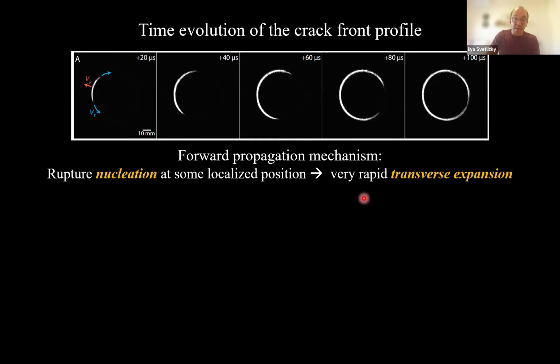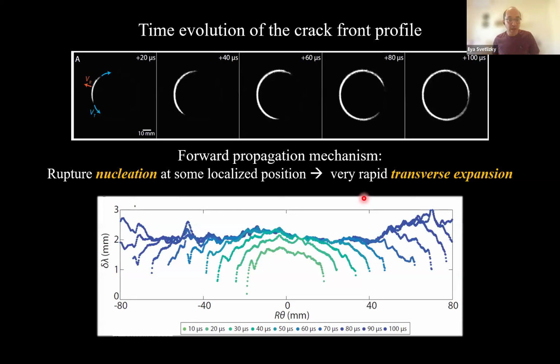So the forward mechanism is that rupture nucleates and expands through a very rapid transverse expansion. So this is how you start with the circle and you finish up with the circle. And we can track the crack front. So the colors correspond to different time steps. The y-axis is the radial expansion. The x-axis is the coordinate along the periphery, the perimeter of the crack, r theta. So it seems like the crack sticks out a nose, and then expands in the transverse direction.